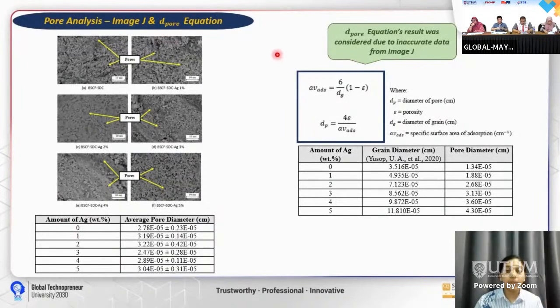And the second method will be the D-pore equation, where the diameter of the pore will be evaluated from the porosity of the samples, the diameter of the grain and the specific surface area of adsorption as well. So these are the tabulated results from using the D-pore equation, where we can see a consistent result. When the amount of Ag is increased, the pore diameter increases as well.